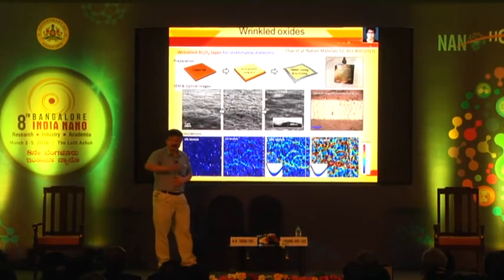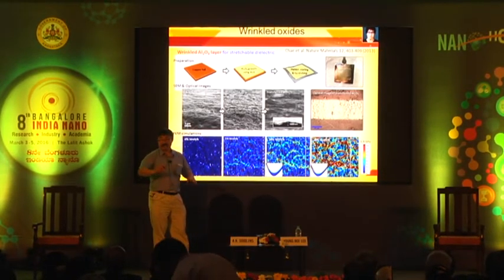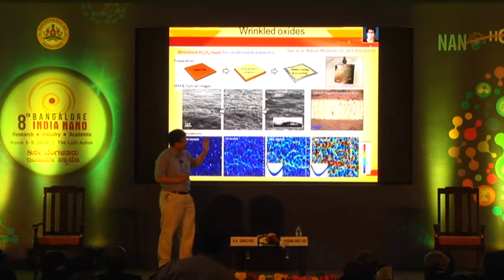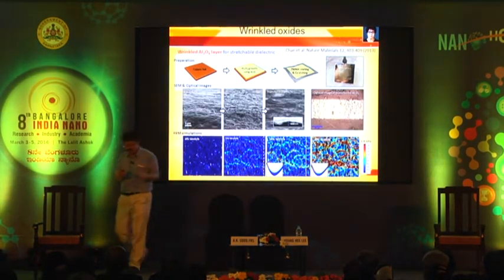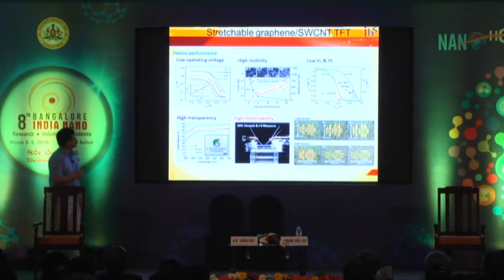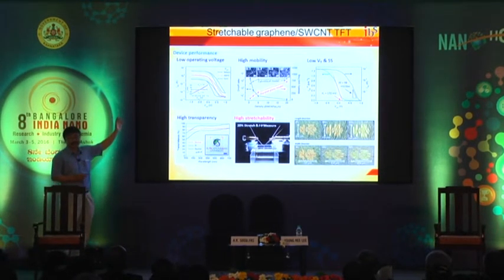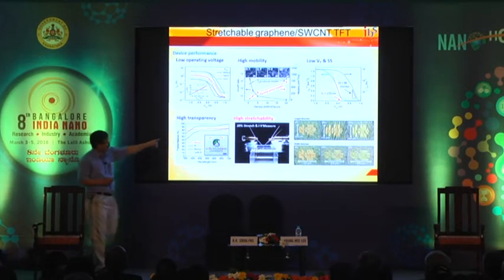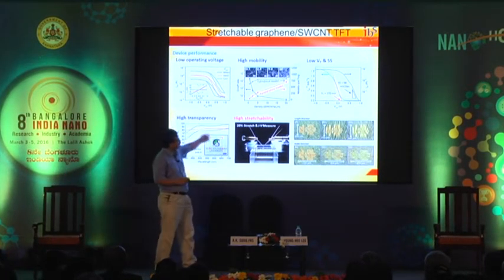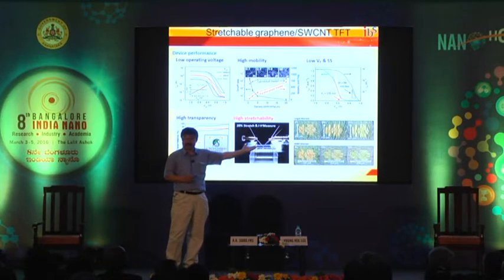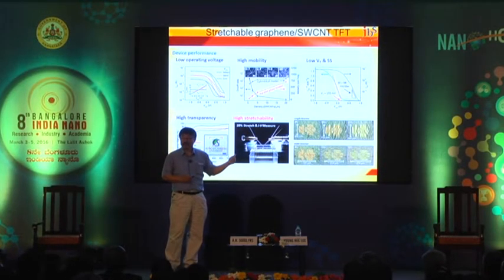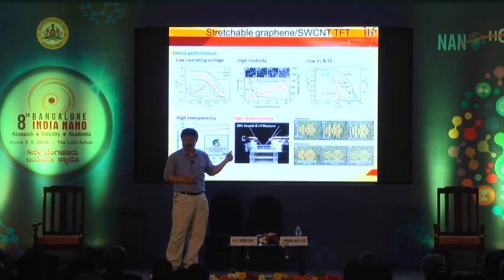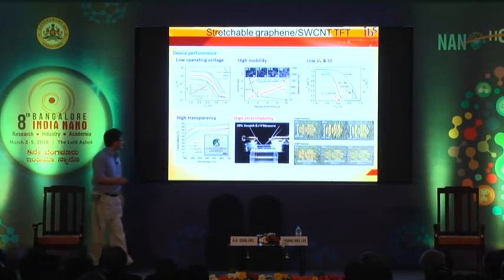So the inner part has a high strain, but the outer side is still maintained okay. So up to 20%, we are quite sure this one should work. In fact, that's actually what happened. All the device characteristics, it works perfectly. And one thing nice is with this approach, even the subthreshold is really close to the ideal value of 60 millivolt per decade. So this is a very high performance device.